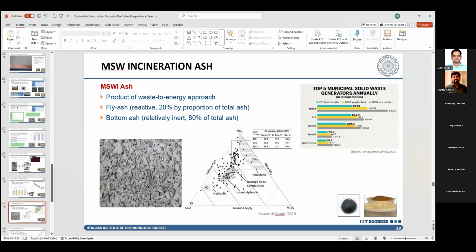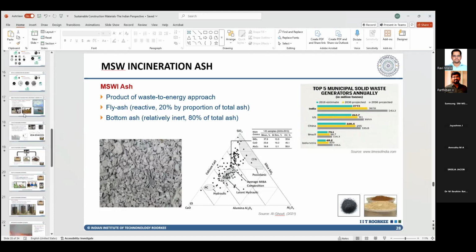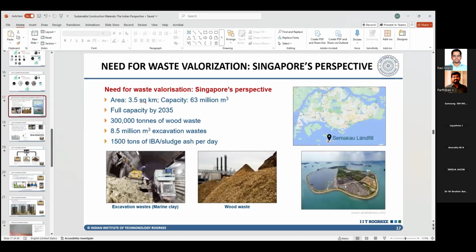By doing so, you have two advantages. You are reducing the volume by about 70 to 80%. More importantly, you are able to generate electricity out of that. When I gave you the example of Singapore, where they are incinerating all their waste and dumping the ash here, they are generating 5 to 8 megawatts of energy, depending on how much waste they're burning. This is in just one plant, and they have 3, 4 similar plants. Though their energy requirements are in thousands of megawatts, still, if they're able to generate electricity out of just waste management, that's a very good idea.